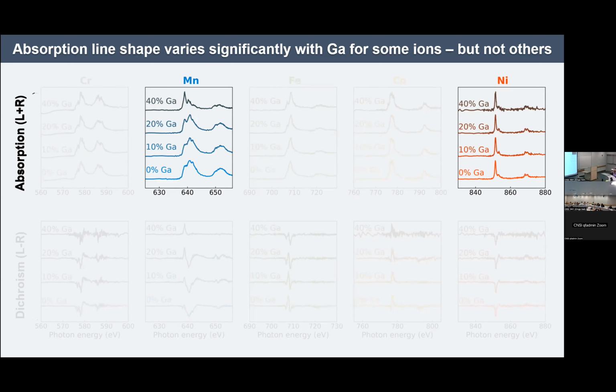The first set of absorption spectra I'll draw your attention to are these nickel scans here, where what you notice as we add gallium in is that the signal to noise gets worse because there's much less nickel by the time we get to the 40% gallium sample. But aside from that signal to noise change, there's no overall difference in the shape of the absorption spectra. So nothing is happening to nickel as gallium goes in. We can describe this 0% gallium spectrum as nickel 2+ in an octahedral environment. And as gallium comes in, nickel just stays on that octahedral site. It changes nothing. But manganese is a very different story.